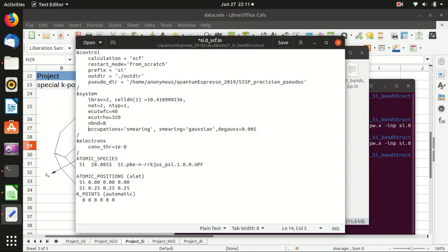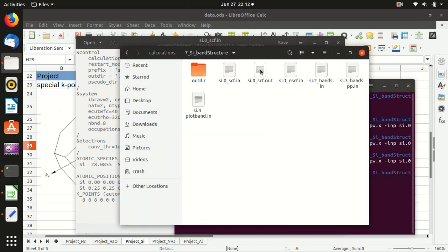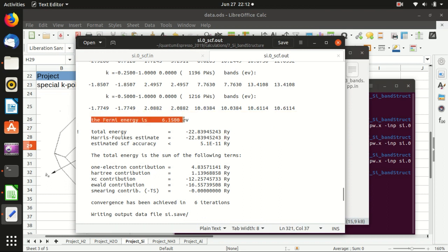Still, whether or not you specify the number of bands, you don't get a Fermi energy in this file. To get the Fermi energy you need a smearing term. Without smearing you are calculating at zero temperature — at zero temperature there is a band gap and the Fermi energy could be anywhere inside the gap. Adding smearing on the Fermi level solves this. When you run with smearing the output file shows the Fermi energy, but no longer outputs the highest occupied or lowest unoccupied levels because the smearing means occupation is no longer sharp.